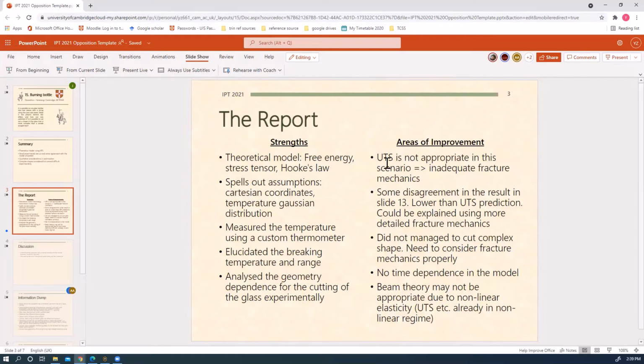I just chose the ultimate tensile strength as a first starting point to get an estimate of which order of magnitude I am working in. And as I could show with the experimental data, I managed to determine more or less precisely the order of magnitude at which the bottles are breaking.